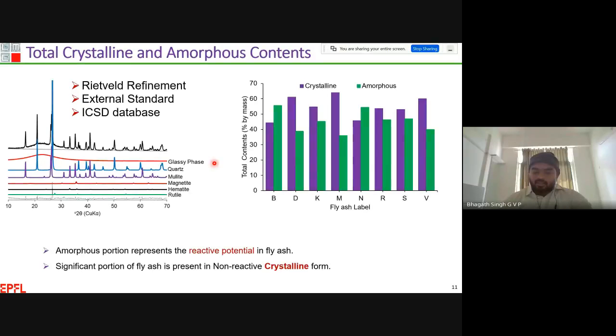And finally, as per our IS standard, these fly ashes are classified as siliceous fly ashes. Even though they are siliceous fly ashes, I would like to call them low calcium siliceous fly ash. In the next step, I have used the Rietveld refinement tool to determine the total crystalline and total amorphous content present in all these fly ashes. And this is the XRD signature of one of the fly ashes, fly ash B, one of the source fly ashes. As you can see here in the fly ash XRD spectra, we have a broad amorphous hump over a 2 theta range from 15 to 32.